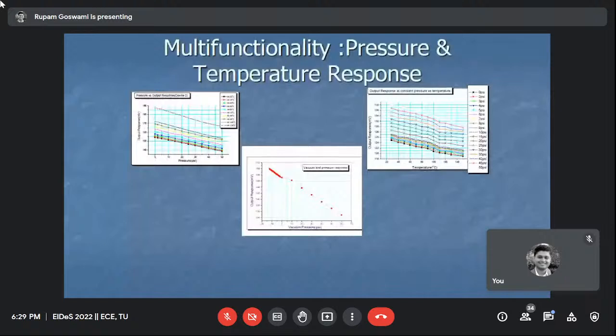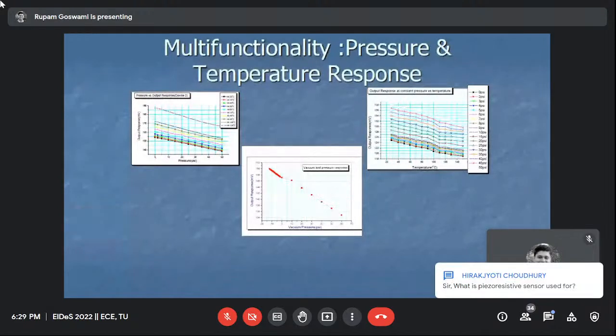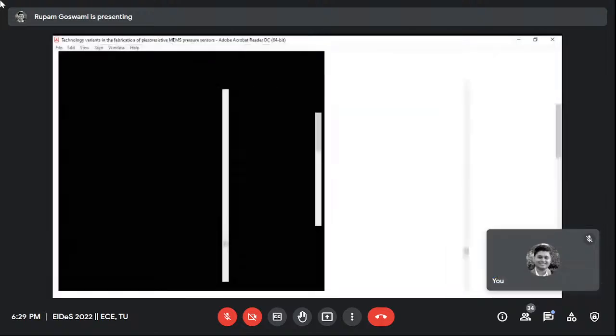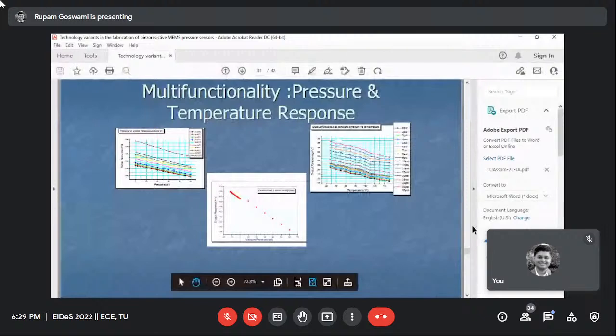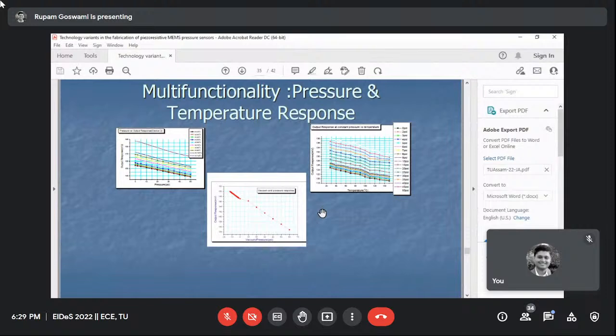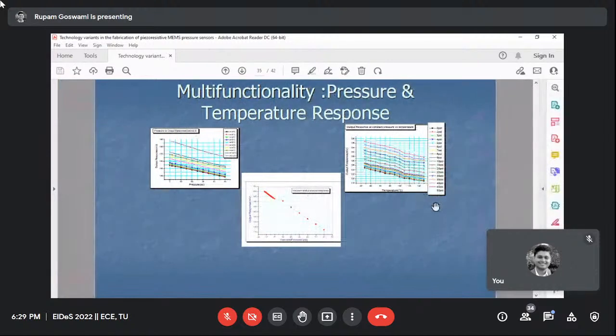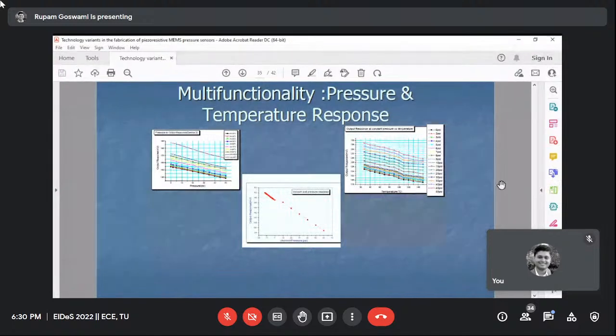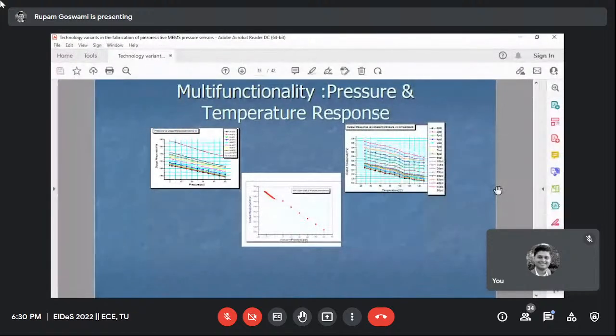Okay, so this is a typical profile of polysilicon-based piezoresistors, where you can see that it can also be a temperature sensor along with the pressure sensor. And here this complete performance has been shown. Then the same chip can be used as a pressure sensor as well as a vacuum sensor if sucking is there, and you can see the slope is almost the same, but there is a gap here, a jump here, when it jumps from pressure to vacuum, so it starts from here.